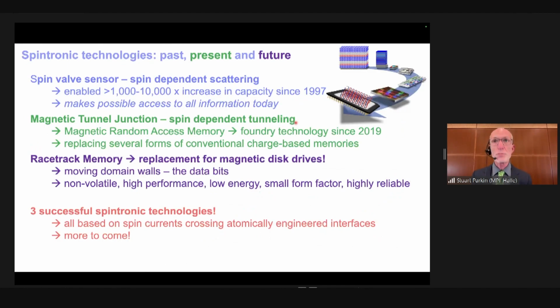I will just summarize by saying that the spintronic technologies have, I think, created very interesting means of storing digital data. On the one case, we developed a spin valve sensor that is 1,000 times more sensitive in the detection of small magnetic fields than any other sensor at room temperature, and basically enabled a more than 1,000-fold increase in the storage capacity of magnetic disk drives since this technology was introduced in 1997, subsequently replaced by tunnel junction devices, spin-dependent tunneling, and we've demonstrated that this magnetic random access memory we proposed in 1995 is viable, and since 2019 it's commercially available from all the major semiconductor foundry companies, and has already sold, I'm told, several $1 billion worth of MRAM, which is fantastic.